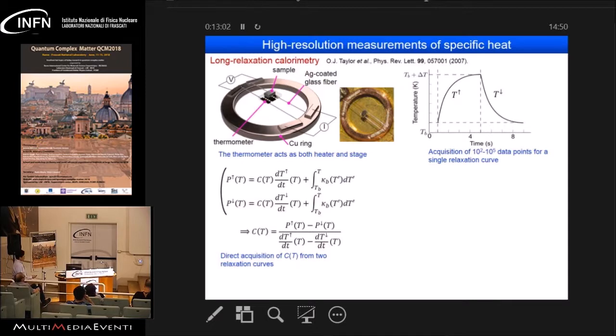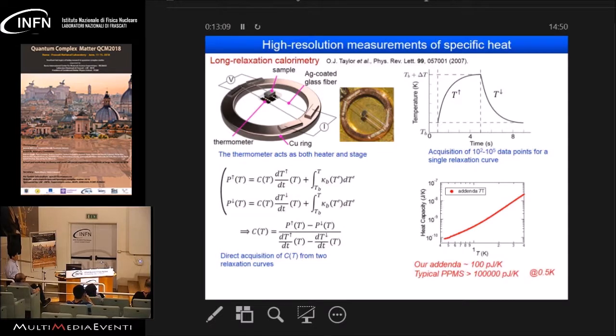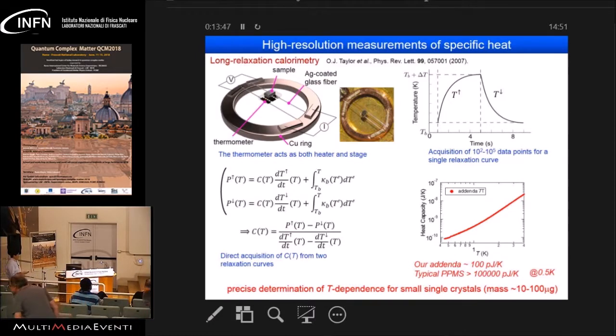And so we developed this kind of homemade calorimeter, which has a very small addenda component, much smaller than the commercial PPMS type. So we can measure the specific heat very precisely for small single crystals with a mass of less than 100 micrograms. And we use the so-called long relaxation calorimetry technique, where we make a large pulse and acquire many data points, up to 10,000 or 100,000 data points, to give the information on the temperature dependence of the specific heat.